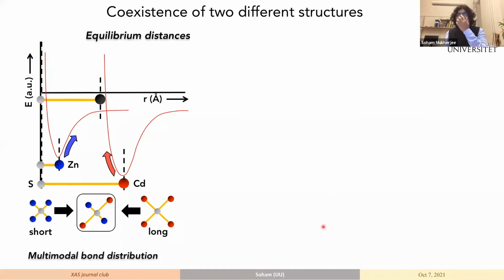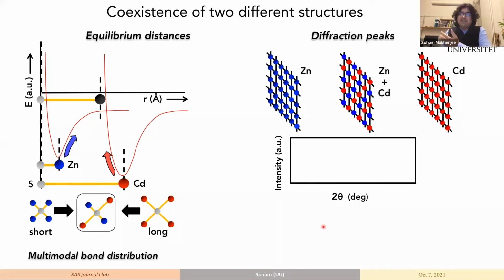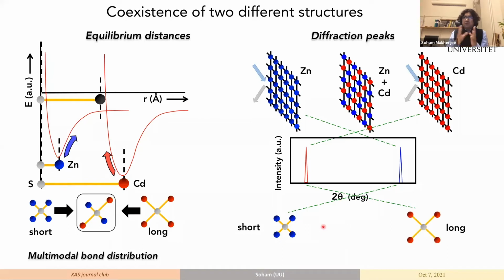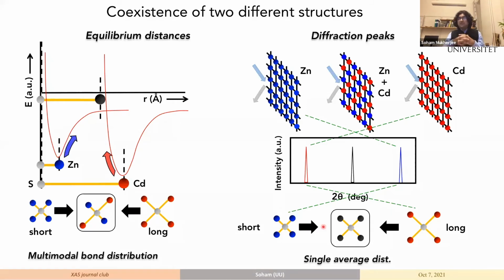So this is basically what is happening: you have individual, very separate distances, and when you probe elements with element specific techniques at the local scale, you'd see a multimodal bond distribution. But when you look at the diffraction, your lattice has both kinds of atoms, and you will have two different kinds of diffraction. And when you have both of them in the system, you will get an average description, which is a single average. So basically, when you look at all the different kinds of models, you will see that they always consider that this periodic potential is correct in an average sense. When you translate it down to bond distances, it will immediately collapse.